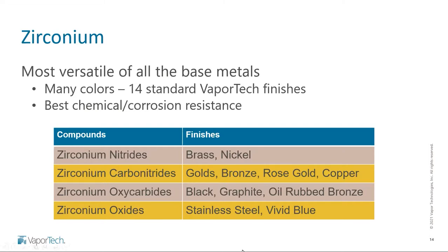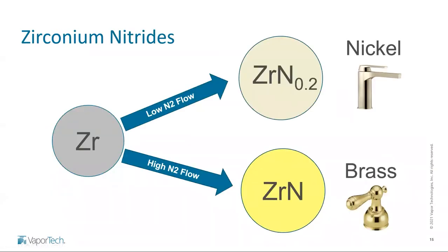So the types of coatings, again, these kind of compounds we talked about before, the nitrides, carbonitrides, wide range of different colors, anything from the brasses and nickels to you start adding some carbon, you start getting some of the redder yellow metals, some of the golds, bronzes. We're going to talk a little more about our oxycarbides, which is a unique coating family where we get some of our blacks and graphites, and then zirconium oxides, where we get some things like some stainless steels and blues. So just an example of how we can use the same compound but get wildly different colors.